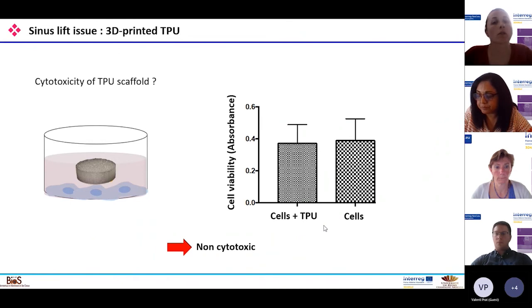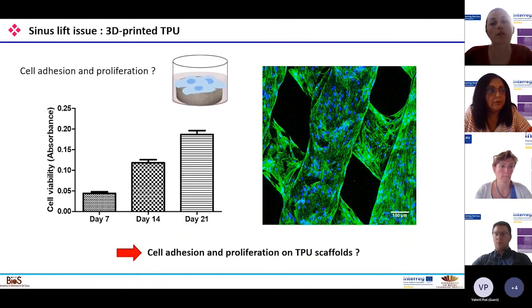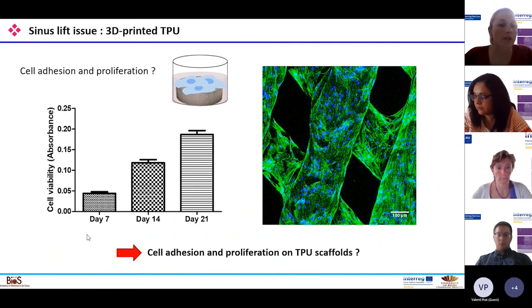The next step was to check if the cells adhere and proliferate inside the scaffold. For this experiment, we seeded the stem cells directly on the scaffolds, and we checked their viability at day 7, day 14, and day 21. What we observed is an increase of cell viability over time. This cell proliferation and adhesion was confirmed by the cell labeling on the scaffold. As we can see here, you have a lot of cells aligned on the fibers of the scaffold.